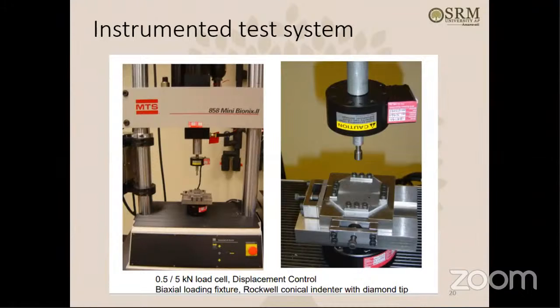Every quarter rotation of the screw was calibrated to some step of loading. We put a strain gauge on the specimen, and accordingly we measured the loads, whether tensile or compressive, whatever stresses are there. For the indentation, the indenter was a Rockwell-type conical indenter with a diamond tip.